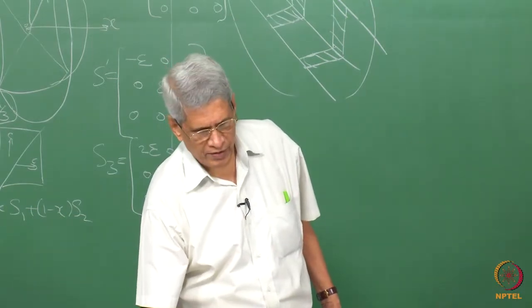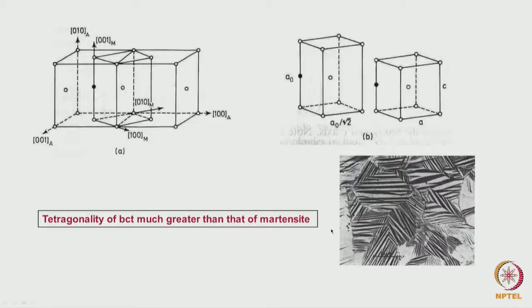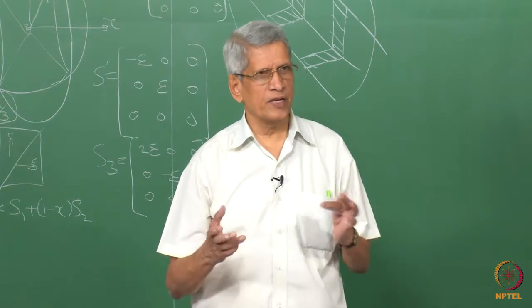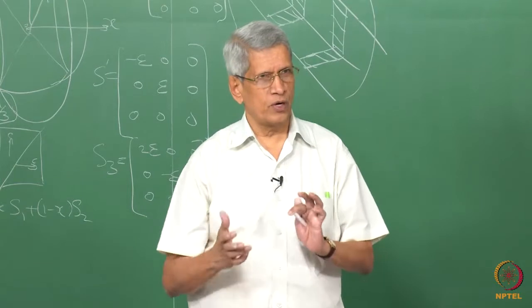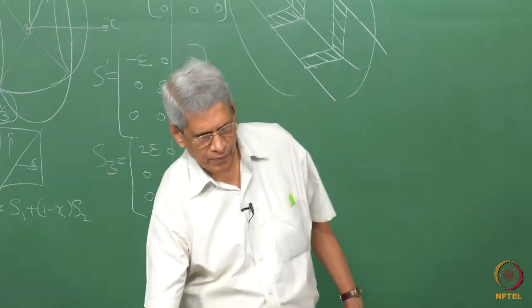So we have a correspondence relationship. Now, that is exactly what is being shown. Typically, this sort of martensite, this is a plate martensite, is essentially a twin-related structure. As I mentioned, why twinning is required: this twinning is responsible for compensating, to make the strain in one direction zero.